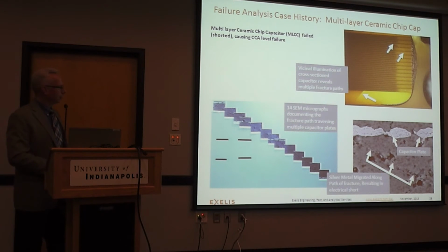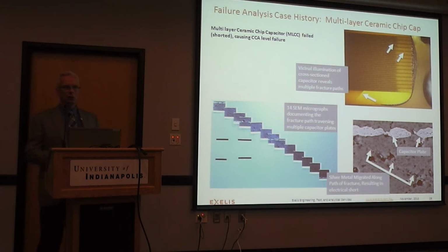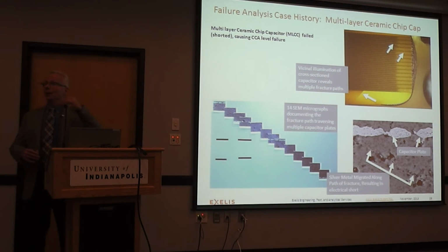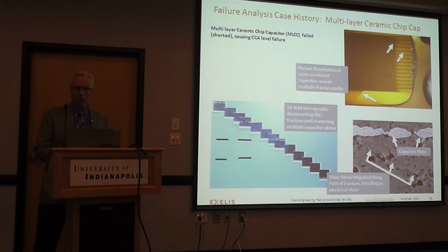And now this image over here is a picture of a wall in our lab. We pinned up a number of high magnification SEM images showing how the fracture traverses from one plate to another plate to another plate to another plate. And in most of this fracture path, you can see silver metallization migrating along that path. That migration of silver metallization along that fracture path is what caused the electrical short.